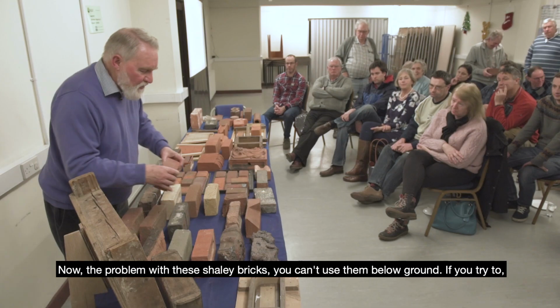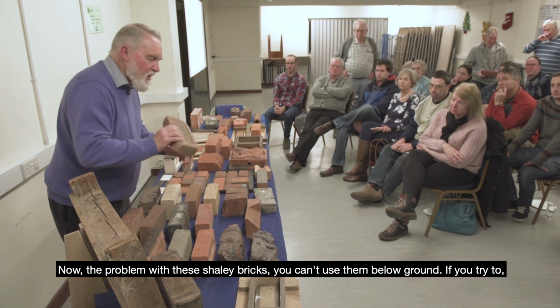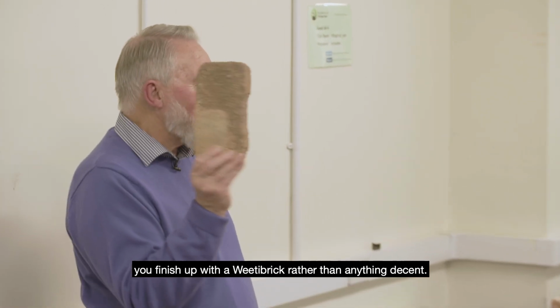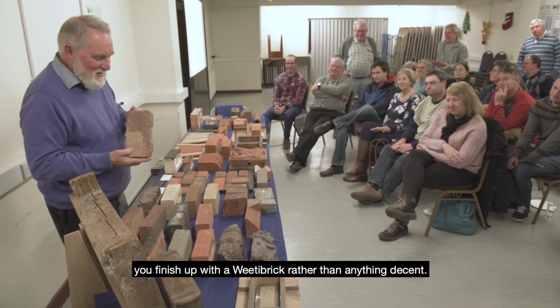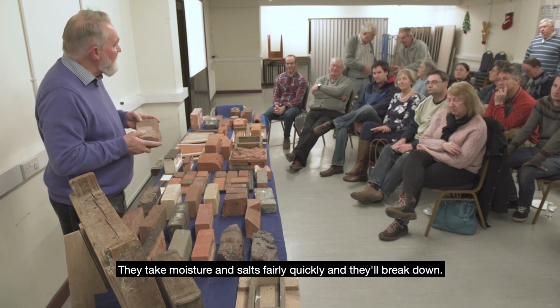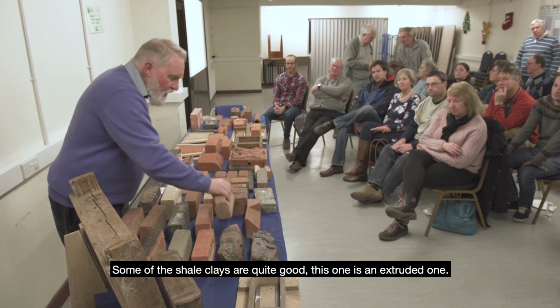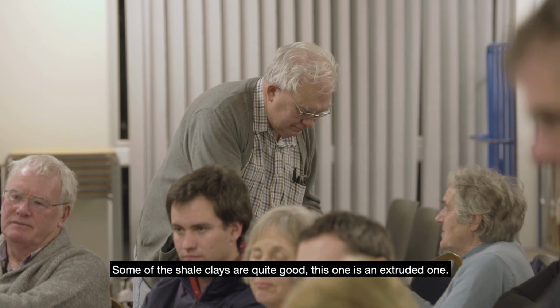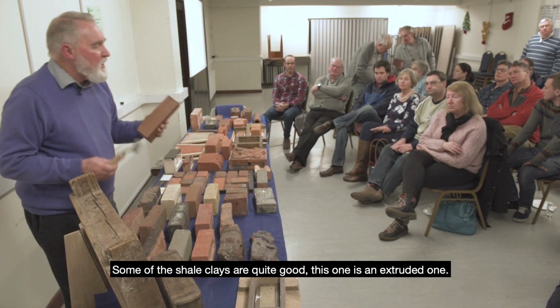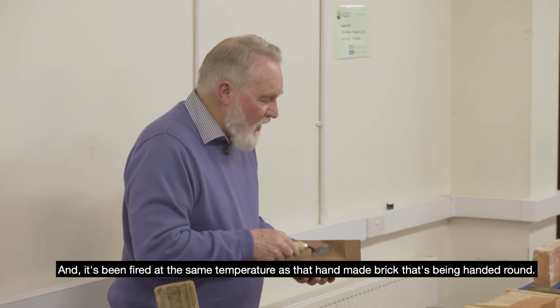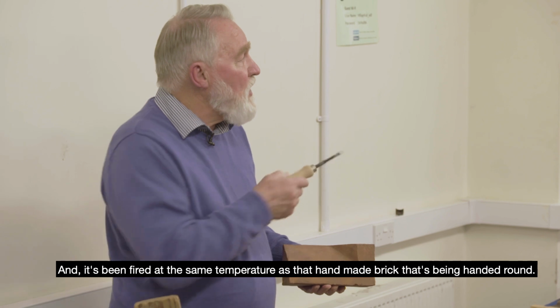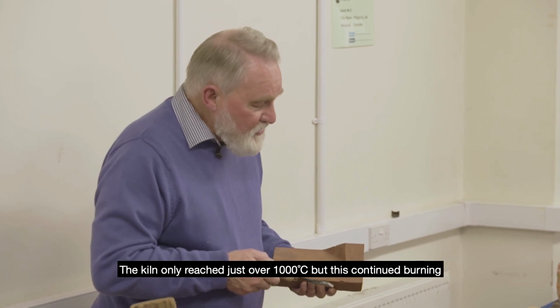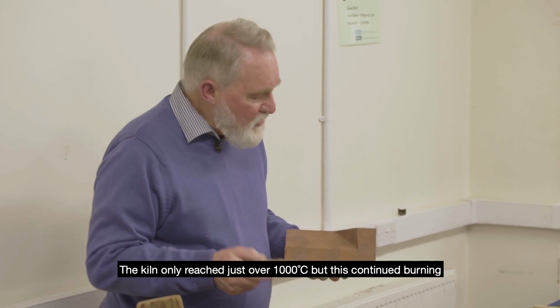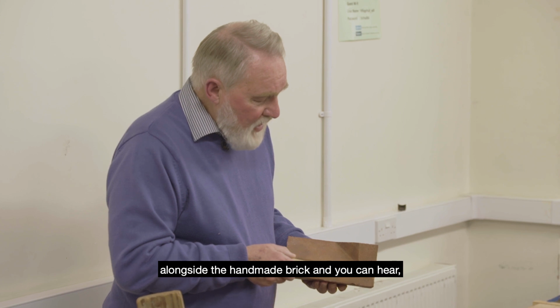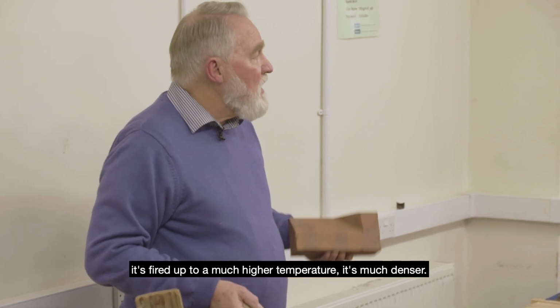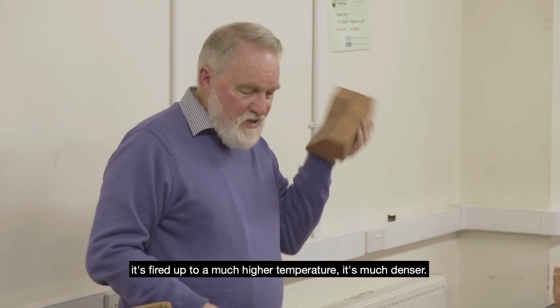Now, the problem with these shaly bricks, you can't use them below ground. If you try to, you finish up with a mushy brick rather than anything decent. They take moisture and salts fairly quickly and they'll break down. Some of the shale clays are quite good. This one is an extruded one, and it's being fired at the same temperature alongside that handmade brick that's been handed round. The kiln only reached just over 1,000 degrees, but this continued burning alongside the handmade brick, and you can hear it's fired up to a much higher temperature. It's much denser.